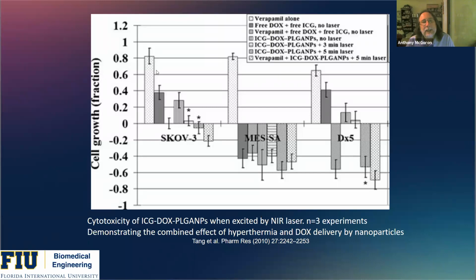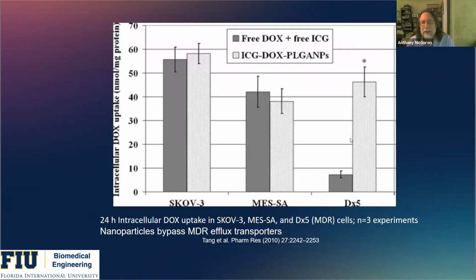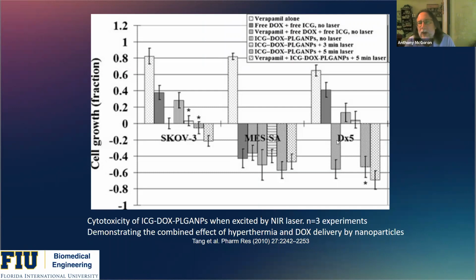We see an expected response in the SKOV-3 cells, and the MES-SA cells, it's easy to kill these cells. They're very sensitive to chemotherapy. But with the DX5 cells, we see that delivering the drug by nanoparticles to multi-drug resistant cell lines, we have, first of all, we could increase the effect of free drug by delivering verapamil, and that's been tested and even studied clinically, although I don't think it's ever been made practical, and so it's really not an option clinically. But we could increase the uptake, and that would be terrific.